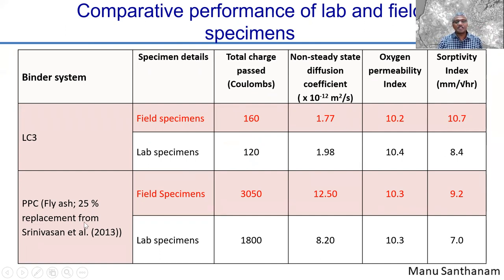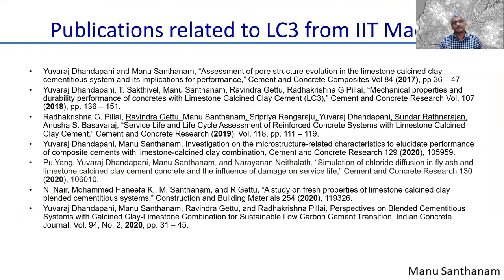In the case of the fly ash based concrete, you see this difference here. Major difference. The lab specimens perform much better than in the field. So that means your fly ash based concrete is more susceptible to on-site curing as compared to LC3 based concretes. So that's the major benefit of utilizing LC3 over fly ash concrete for field applications.